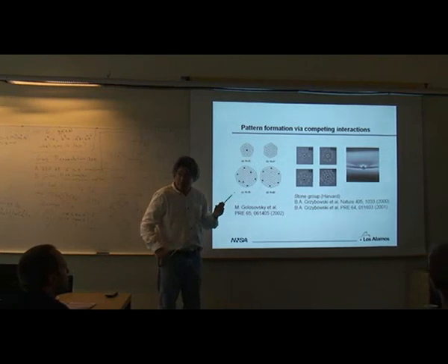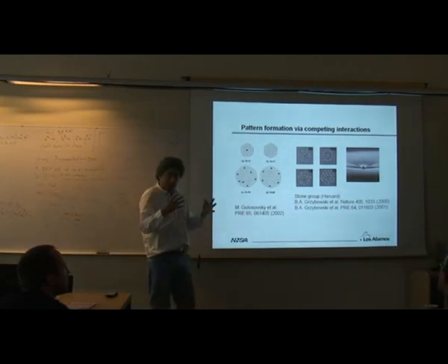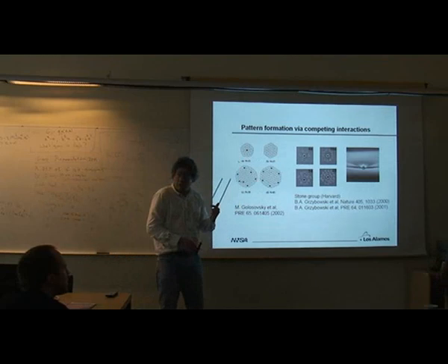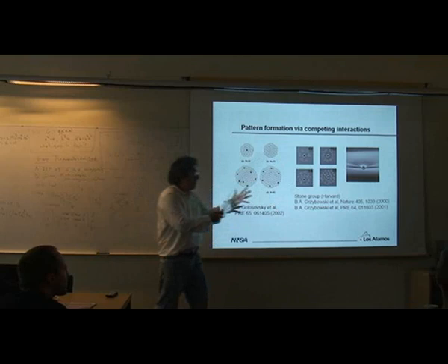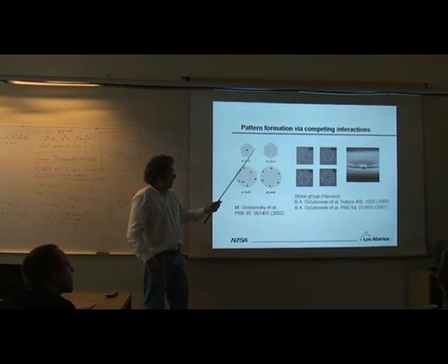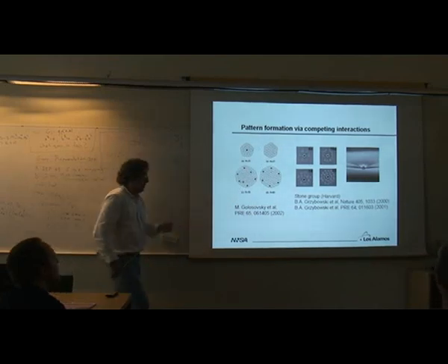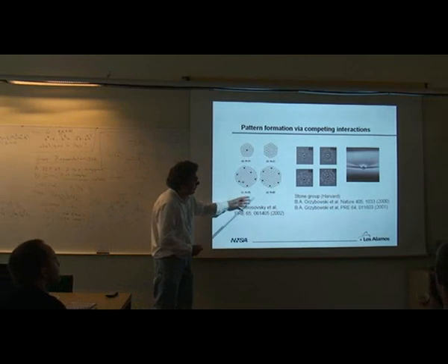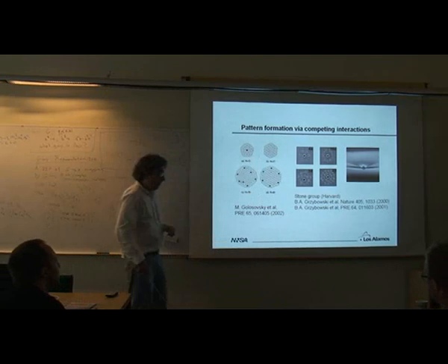Okay, I see. So once they create these substructures, you can test the stability by, for instance, changing the charge. You can make it less screened by changing the salt. You remove the salt or the stuff that would screen it. So the thing wants to break up, right? Because eventually it becomes unstable. And if it's in this configuration, it will like to stay in that configuration longer than this one. And so n equals 70, so there's some defects, 85. And you mentioned 13 the other day. I believe that's one that forms a nice sub-hexagonal pattern.